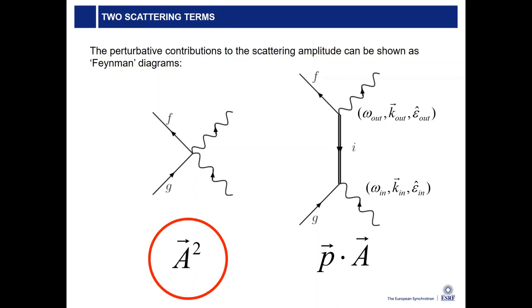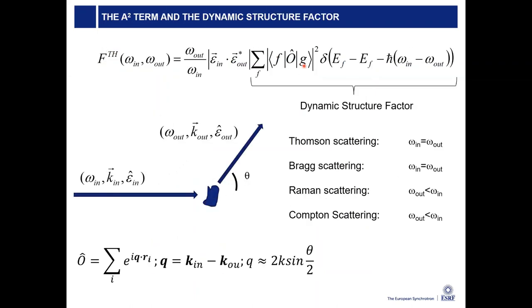Okay, for the A square term, the formula is just for your information, but what is important is that there's a dot product between your incoming and outgoing light. This dot product gives an angular dependence to the intensity. There's elastic scattering, Thomson or Bragg scattering, which is elastic, and Raman scattering and Compton scattering are so-called inelastic terms.